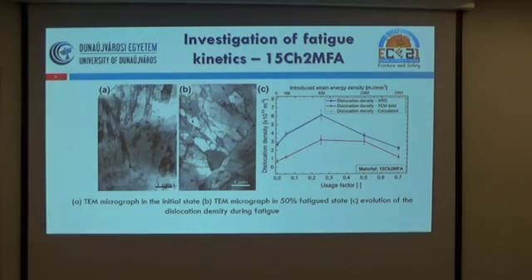We investigated the fatigue kinetics. We have made TEM, transmission electron microscopy, in various stages of the fatigue life. That shows here an initial state, and here a bit later, which is about 50% of the fatigue life. And then in this graph you can see the evolution of the dislocation density, which was calculated in the various stages. These pictures are just illustrations. We made it in more precise stages.